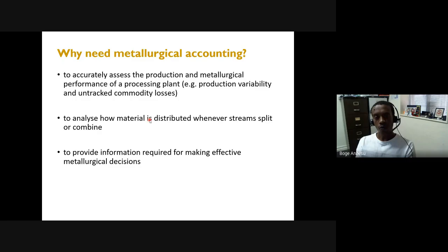Then the figure will show you the grade or the recovery and so on. So you could say 90% recovery was our plant performance. Maybe you targeted for that, maybe target below or above that, then that's how you assess the performance. If it's below performance, usually it's to do with how you operate the plant, of course, but also what were the variations in mineralogy during the year, okay, and things like that. But in any case, metallurgical accounting is very critical.